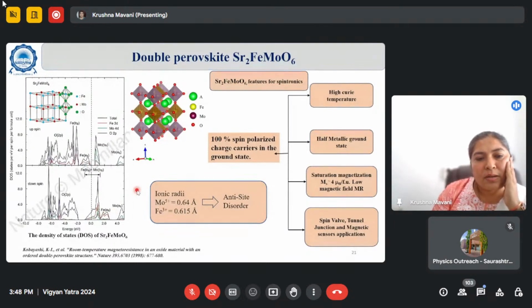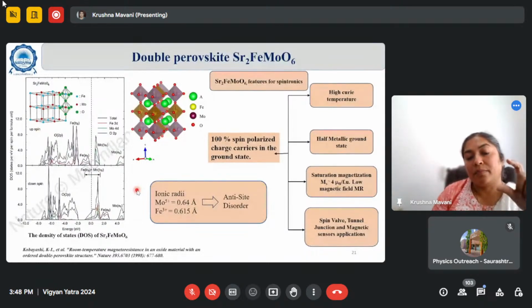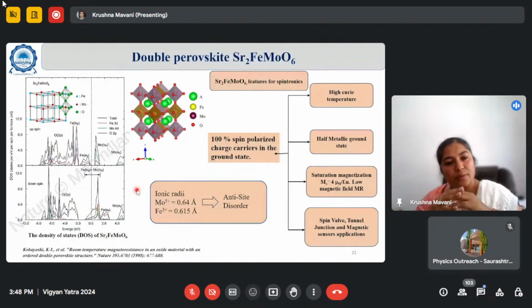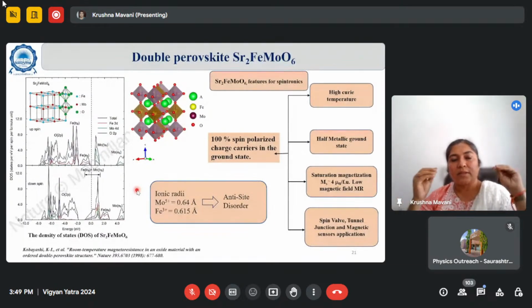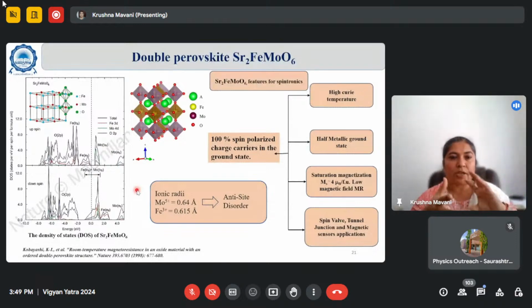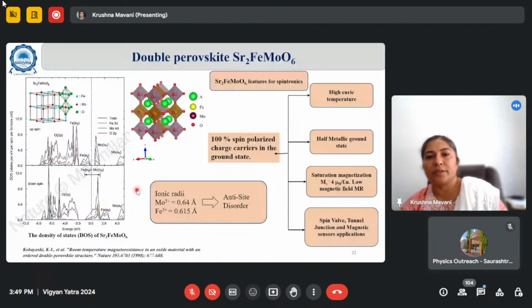So you see there are two spin channels, spin up channel and spin down channel, if it is perfectly ordered in alternate fashion. Spin up having a gap is a semiconducting channel. Spin down having overlapping orbitals is a metallic channel. So when you conduct the charge, there are two channels operating simultaneously. That we'll see further.